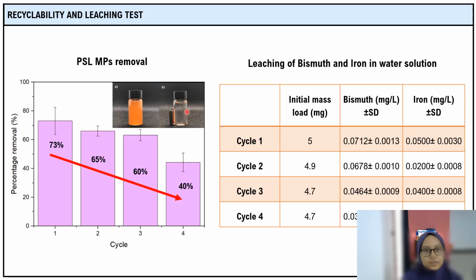This figure shows the recyclability performance of the bismuth magnetic microswimmers. It can be observed that the bismuth magnetic microswimmers can be recycled until the fourth cycle with a reduction of 33% in percentage removal of polystyrene microplastics. The table shows that there is slight leaching of bismuth and iron. The leaching of bismuth and iron is still below the allowable limit, which for iron is 0.3 mg per liter. Meanwhile, for bismuth it is 0.5 mg per liter.